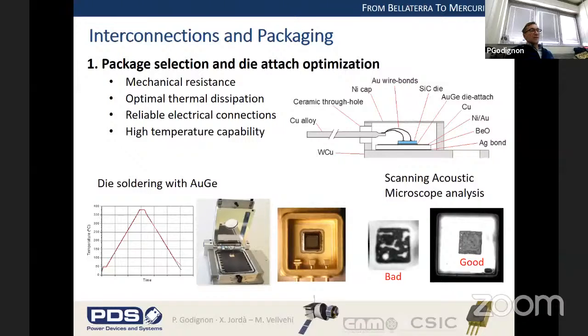So we optimize the solder alloy and we choose gold germanium, which is not commonly used in industry because the process is very difficult, the repeatability is very difficult to control. But in our case, we were able to have a reliable process with a good repeatability. And to check this process, we use a scanning acoustic microscope, and you can see the results. So we make a picture of the interface between the die and the substrate. And if you see here this white area, it corresponds to air which is present between the die and the package. So this air will affect a lot the performance of the device.